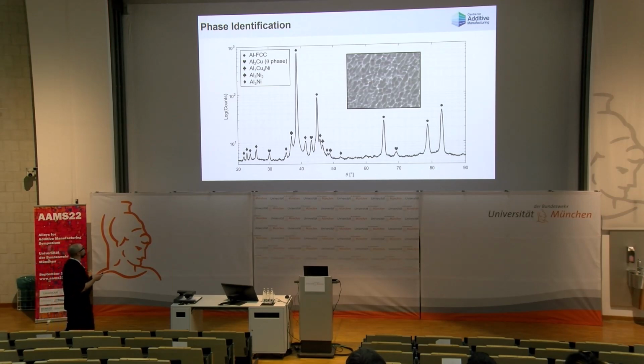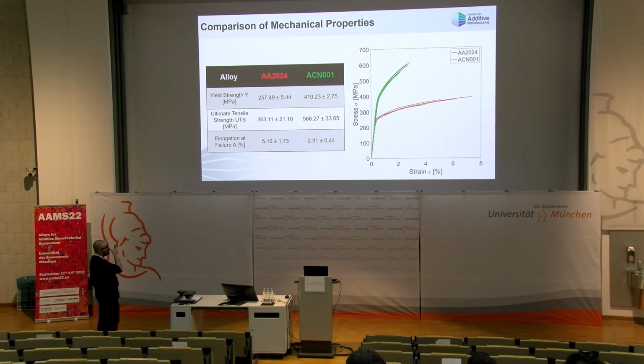This very complex ternary alloy showed very great strength as far as UTS and yield are concerned. But in the as-built state, we show a lower ductility with respect to, for example, 2024 L-PBF.